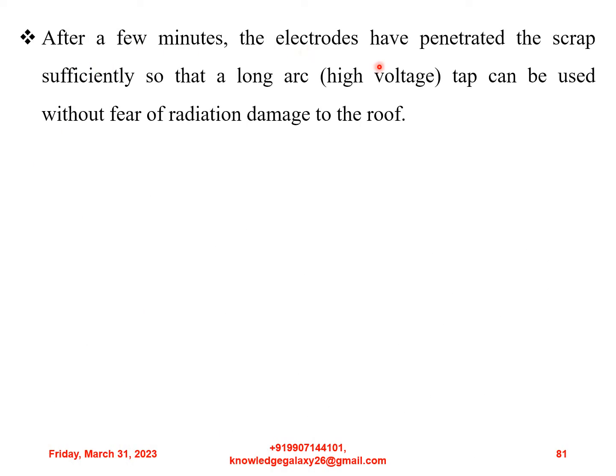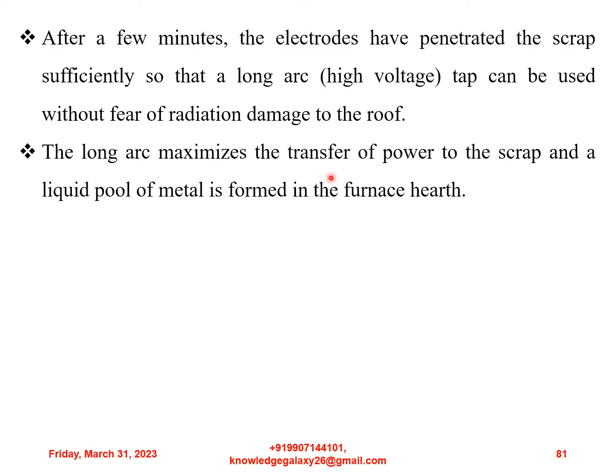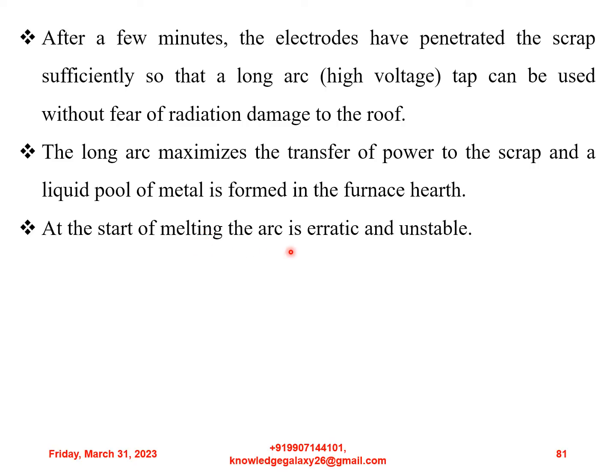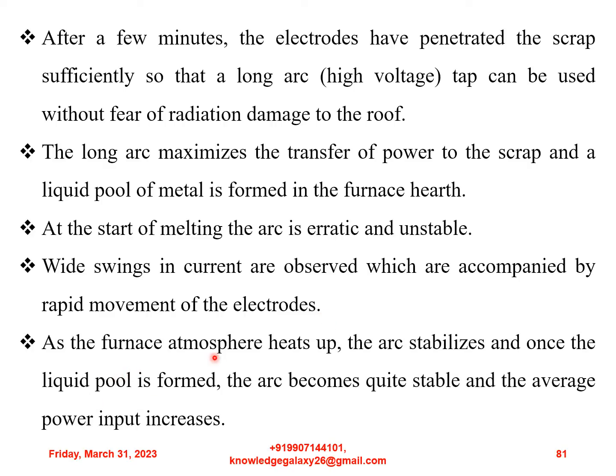After a few minutes, the electrodes have penetrated the scrap sufficiently so that a long arc high voltage tap can be used without fear of radiation damage to the roof. The long arc maximizes the transfer of power to the scrap and a liquid pool of metal is formed in the furnace hearth. At the start of melting, the arc is erratic and unstable. Wide swings in current are observed which are accompanied by rapid movement of the electrodes. As the furnace atmosphere heats up, the arc stabilizes and once the liquid pool is formed, the arc becomes quite stable and the average power input increases.